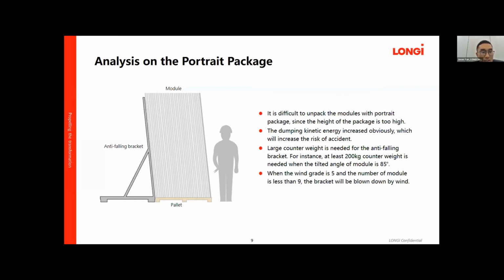So this will increase the risk of accident. And another issue is that if we want to ensure the system is stable, we need to add an anti-falling bracket beside the modules. That means, for example, at least 200 kilograms of counterweight is needed when the tilt angle of the module is 85 degrees. And furthermore, when the wind gradient is 5 and the number of modules is less than 9, the bracket will be blown down by wind after calculation. So that means if we use the portrait package, there are a lot of limitations and an increased risk of accident.